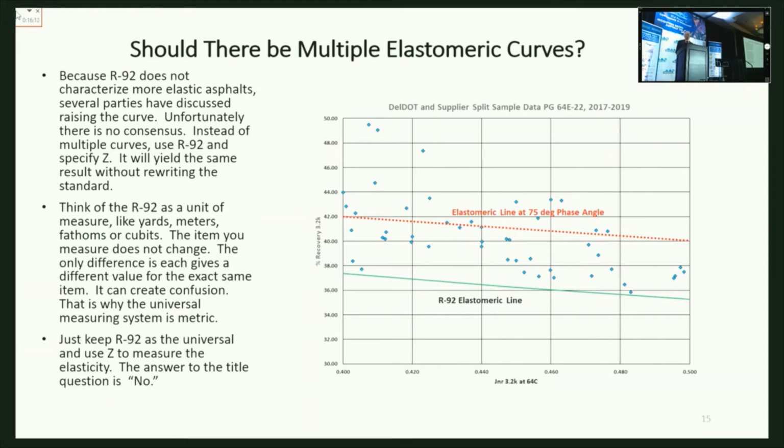So the answer, my answer, is no. Just use a Z factor. If you need something more elastic, specify, I want a Z of +5. That will push up the curve. Or in Tom Bennett's case, I want it to +25. So please don't make multiple curves.